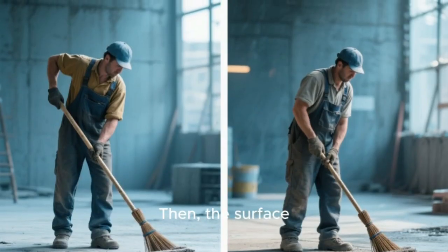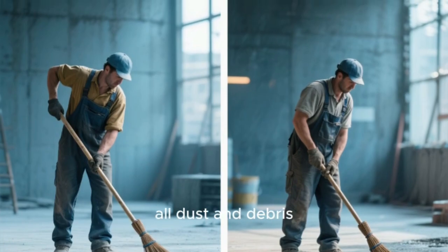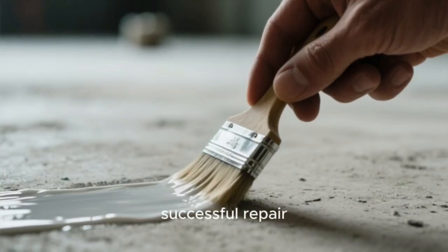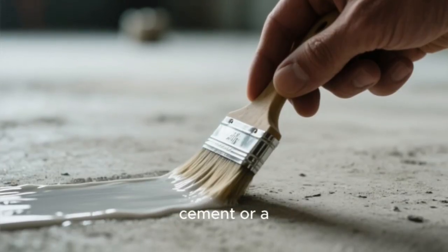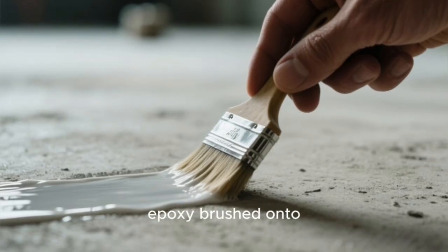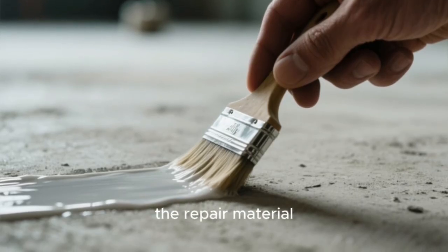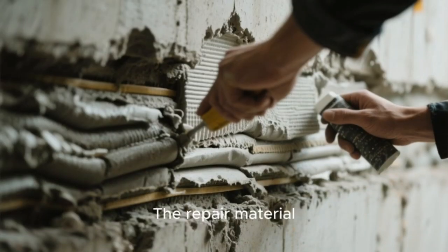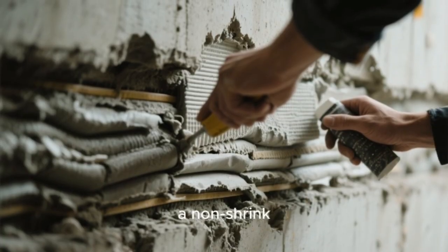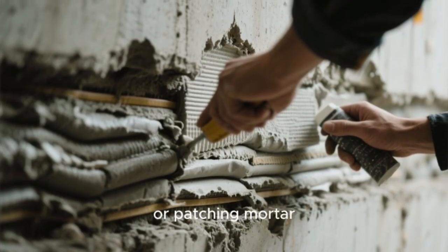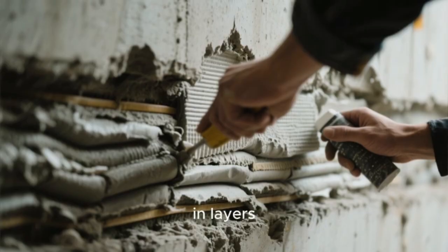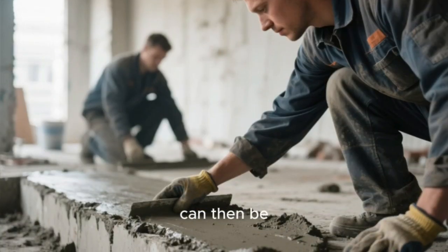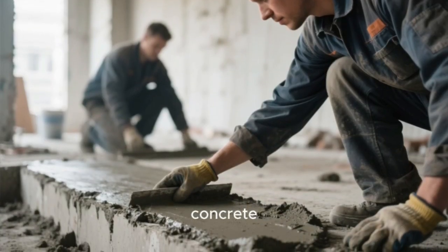Then, the surface must be cleaned of all dust and debris. The key to a successful repair is the bonding agent, a slurry of cement or a specialized epoxy brushed onto the prepared surface just before the repair material is applied. The repair material itself is typically a non-shrink, high-strength grout or patching mortar, packed in tightly in layers. The final surface can then be finished to match the surrounding concrete.